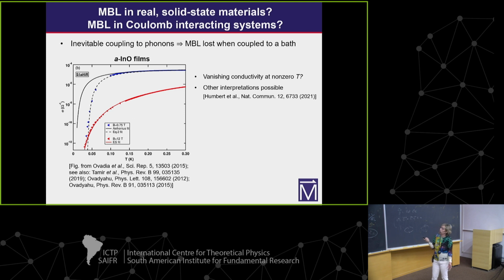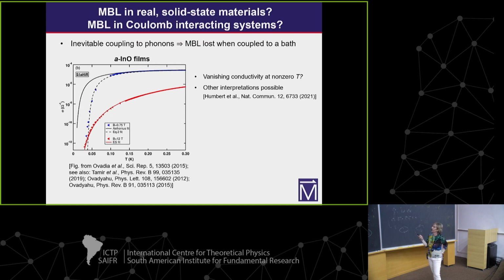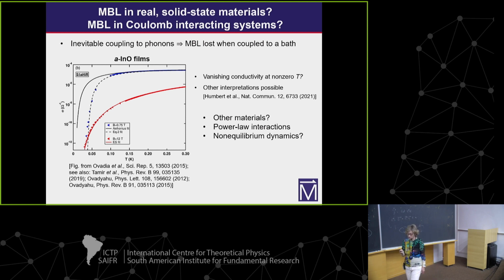There was a report on some amorphous indium oxide films of what appeared to be conductivity vanishing at non-zero temperature, but other interpretations of the data have been proposed. In any case, what one really needs is a study of the dynamics in an electronic system, where usually power law interactions are present — this is a case that has been investigated a lot by theorists.